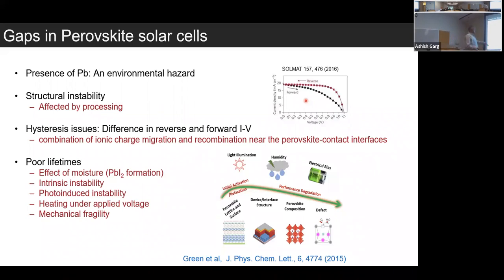And then the biggest problem is the poor lifetime, which could be because of moisture reactivity leading to the formation of lead iodide. There are intrinsic stability issues. Also, light causes instability in perovskites. When you apply high voltages or sweep it many times, that also leads to heating of the device. And of course, there is also an issue of mechanical fragility. So all of these things, despite all the progress in perovskites, have not yet led to commercial realization of this kind of material.